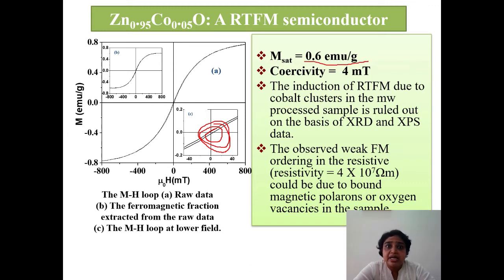So this kind of magnetism is induced in zinc oxide with the help of cobalt doping. The induction of this room temperature ferromagnetism is not due to cobalt clusters, because we did XPS measurement and found there were no cobalt clusters. So basically this is attributed to the induction of magnetism due to the bound magnetic polaron. This is the generally proposed mechanism for the induction of ferromagnetism in the case of zinc oxide doped with cobalt. However, there are still a lot of controversies at this stage also.